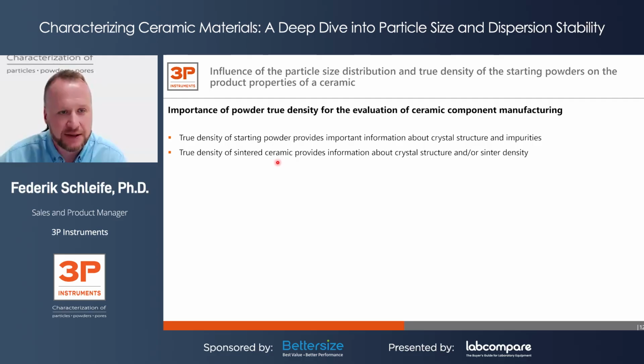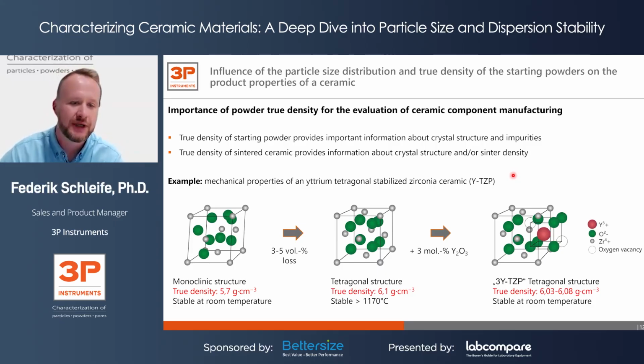And furthermore, on the final sintered ceramic, you can also measure the true density, which gives you again information about the crystal structure, but also about the sinter density. So let me show this to you on one example, how you can identify, with the help of the density measurement, which crystal structure you have, and maybe if it's the right one you want to have. On the example of a zirconia ceramic, I want to let you know that different crystal structures are known. One is a monoclinic structure, which has a true density of 5.7 gram per cubic centimeter. And this monoclinic structure is stable at room temperature.